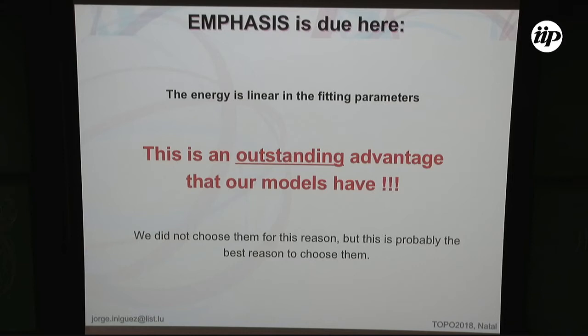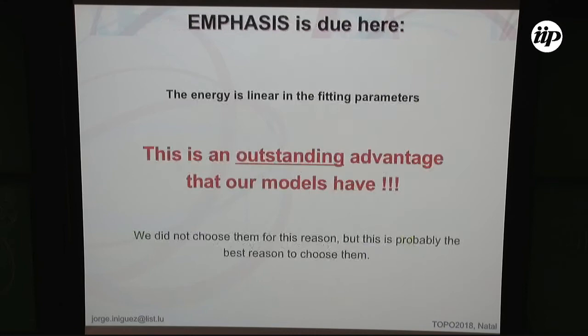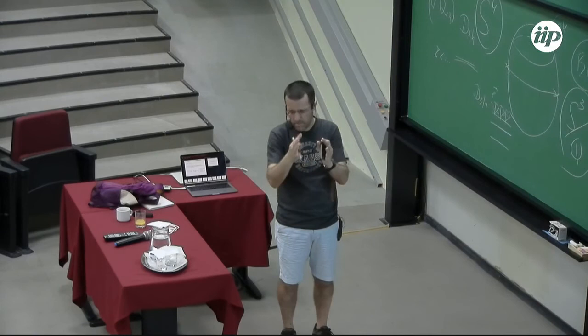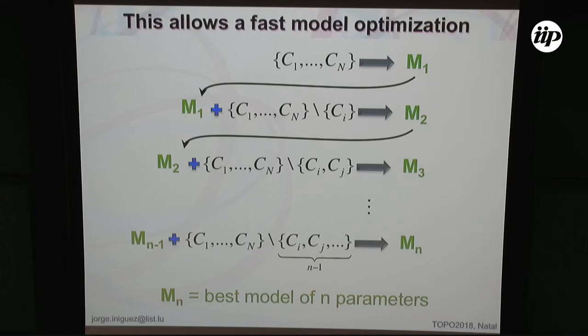Taking advantage of the fast fitting, we first try to find the single most important parameter — the best model of only one parameter. This of course is physically meaningless, but the procedure identifies which parameter best minimizes the goal function among all possible single-parameter models. Once we identify the most important coupling, we fix it in our model and then identify the best second parameter, continuing iteratively until we have the best model of m parameters that is accurate enough.